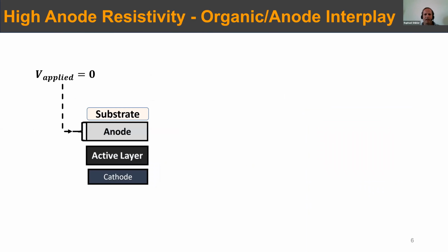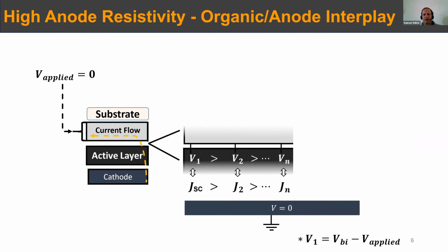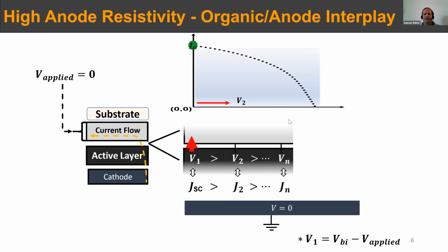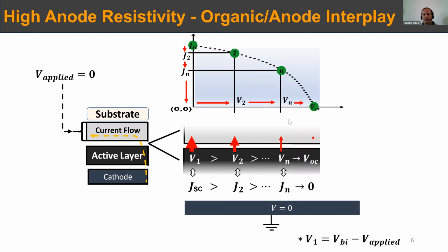So what one can observe is that when you look at the current flow, since the anode has a finite resistivity, there is a voltage development across the anode. As you go further and further from the point where the current is collected, you get a higher voltage. This implies that at this point, the cell feels a bias which becomes closer and closer to the open circuit condition. And if you get far enough from the collecting contact, your system goes into open circuit, and there is no point in increasing the size of the device, because it won't improve any